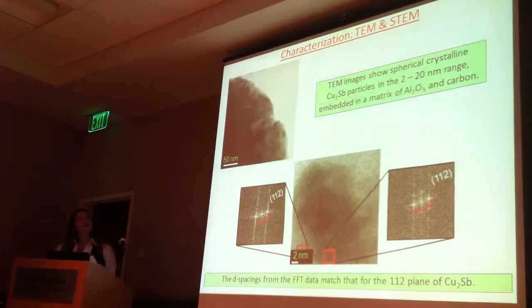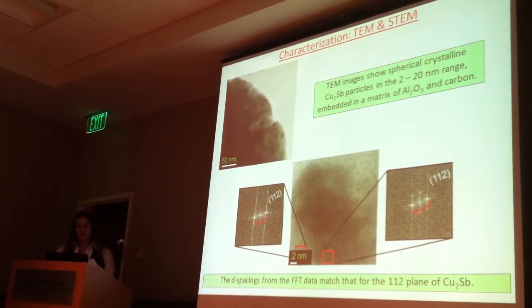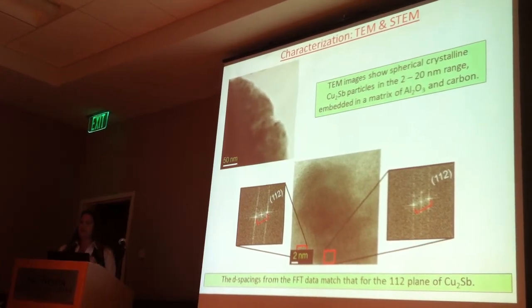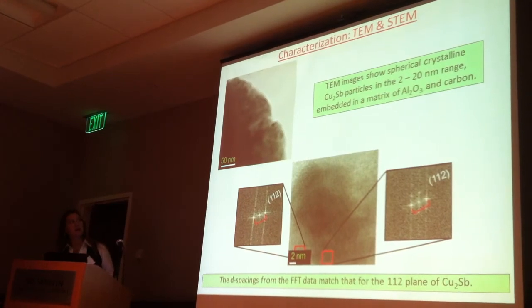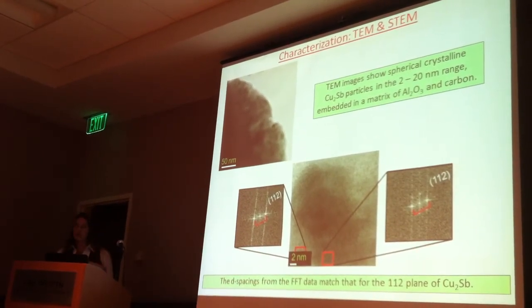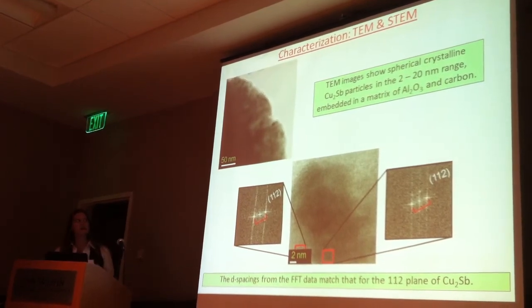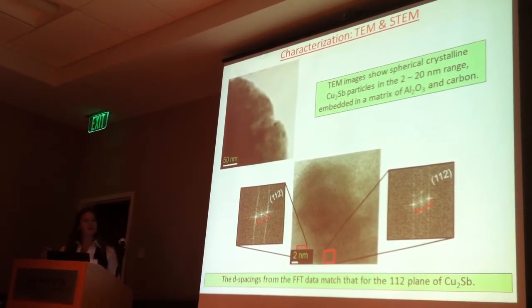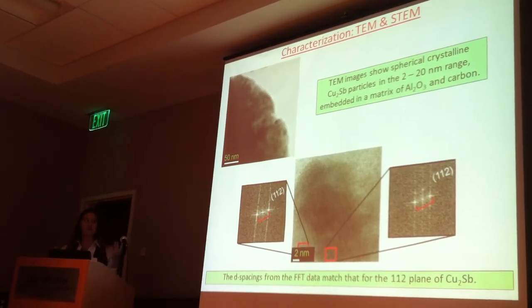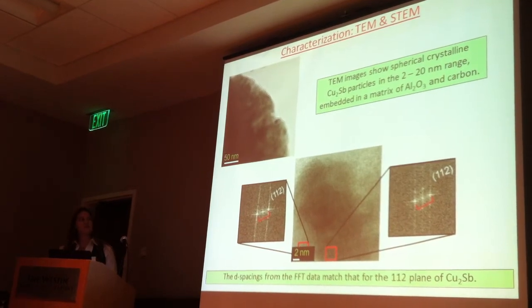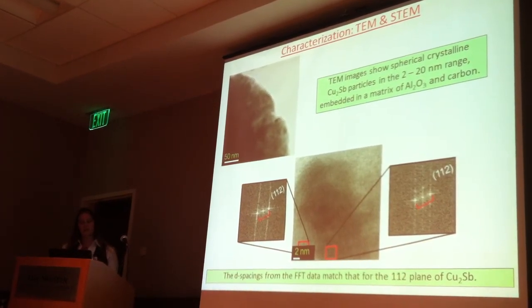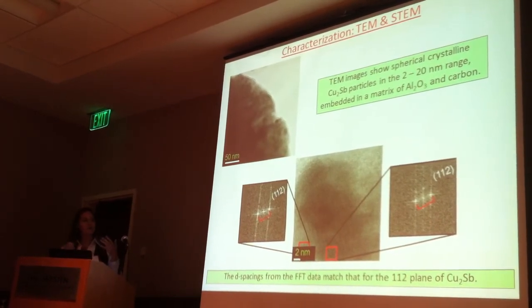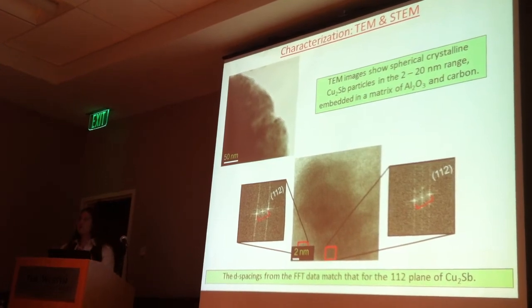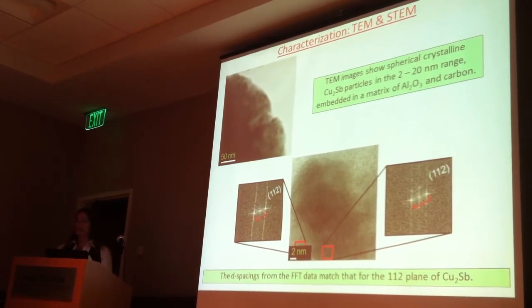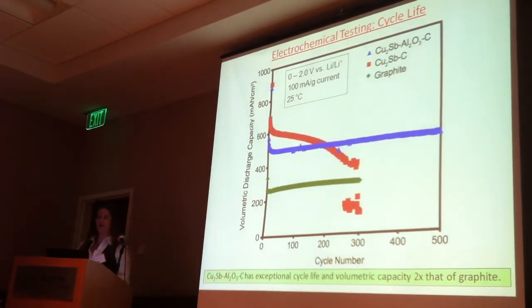So we looked at high-res TEM and high-res STEM to see if our particles were crystalline and maybe figure out what the structure was. What we found from TEM was that we had very small, spherical, crystalline particles, about 2 to 20 nanometers in size, embedded in this matrix of aluminum oxide and carbon. And when we did an FFT analysis on our high-res STEM images, we found that yes, we do have Cu2Sb as our crystalline phase. The d-spacings matched up with planes for Cu2Sb. So what we have is a material that is very small, spherical, crystalline particles embedded in a matrix of aluminum oxide and carbon. And so now you can see how it performs.